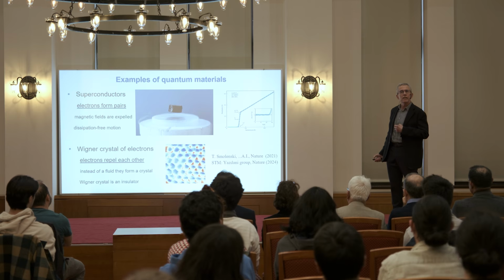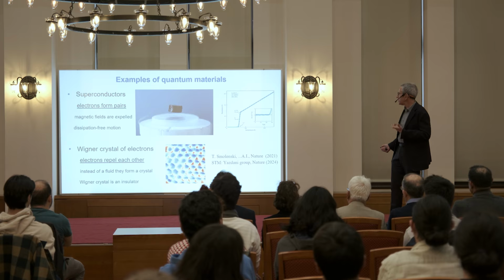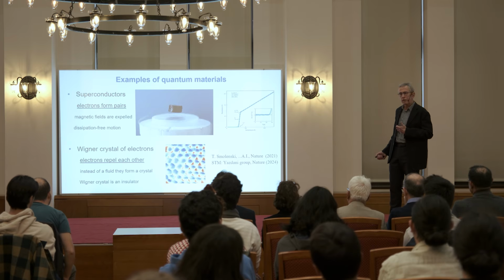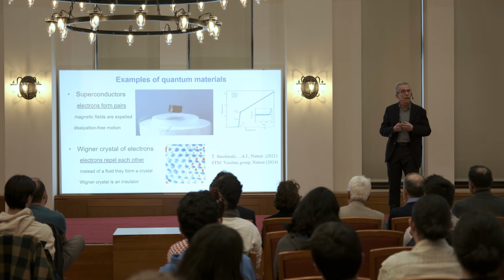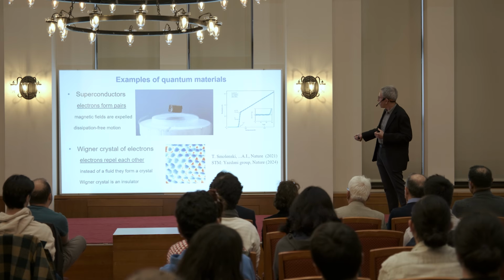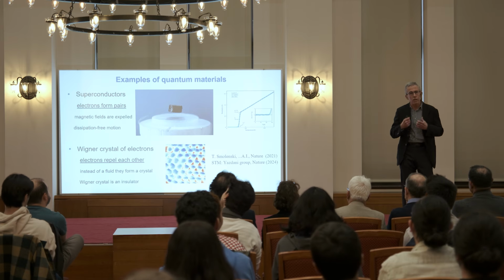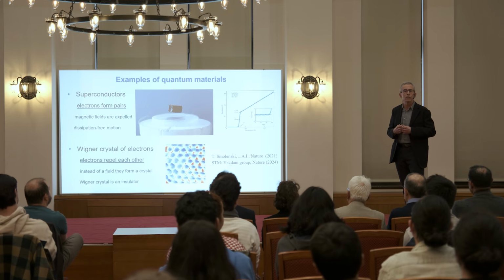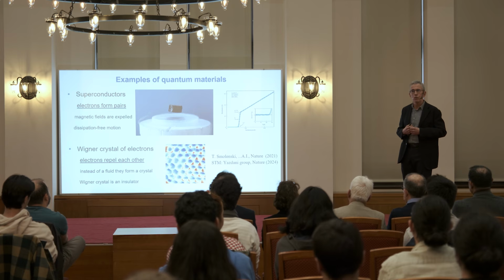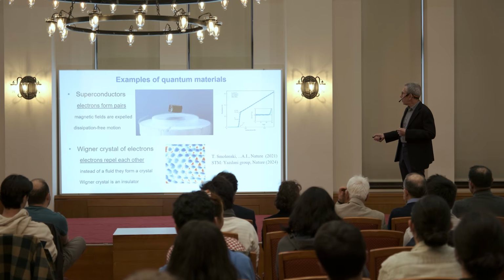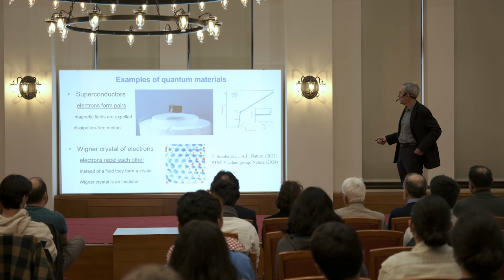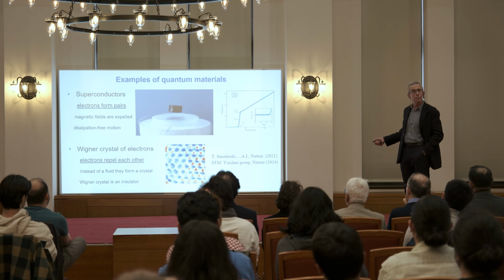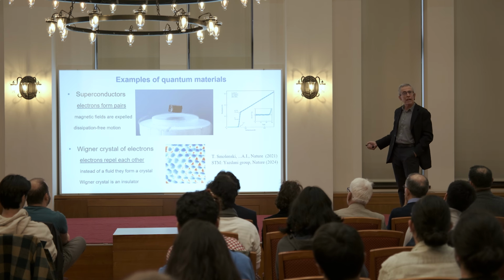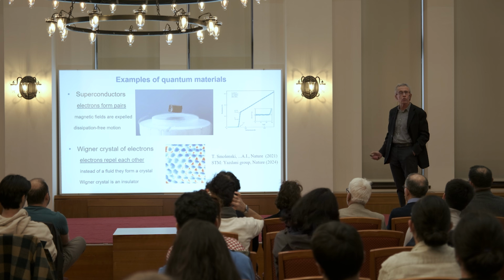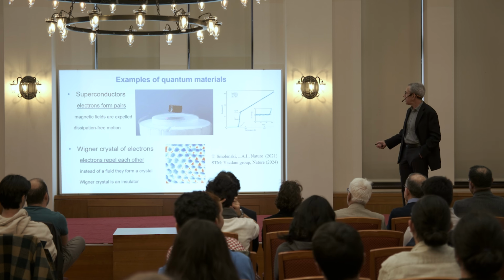So this is, let's say, the typical signature of a superconductor, and you can see that if this temperature were above room temperature, this could be technologically very important, because that would get rid of heat generation in the transfer of electricity. Okay. Now, these also have other fabulous properties, that they're perfect diamagnets, so they expel magnetic fields, and this is something you can use to basically levitate magnets above a superconductor.